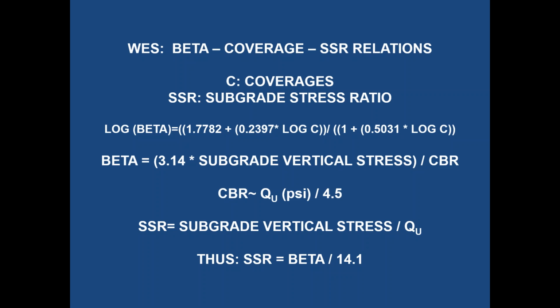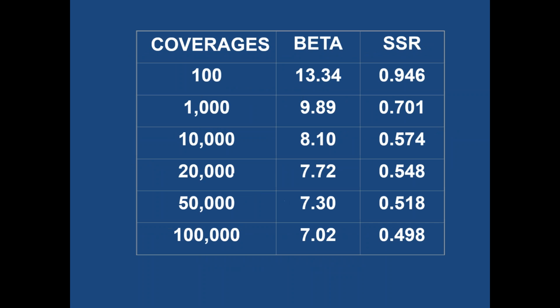C is what? Coverages. Now, coverage is a magic approach that the Corps uses to translate mixed traffic back into, quote, a value called coverage. So it takes into account the wander. And so if you look at it, you find that if you convert CBR back into QU, the subgrade stress ratio is the beta value divided by 14.1, okay? Look at this. This is a plot of beta versus subgrade stress ratio. Sure enough, if you want it to last a long time, you want a what?